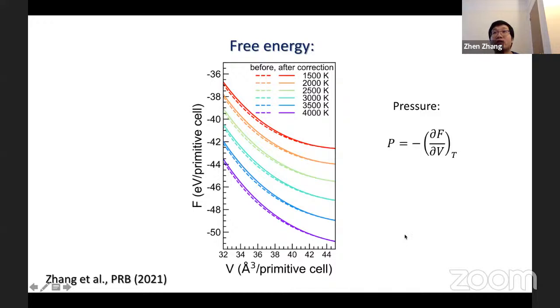Next, the free energy was obtained by entropy integration. Results obtained before and after the EOS correction are shown as dashed and solid curves, respectively. Note the DFT energy correction is temperature independent and does not include anharmonic effects. Anharmonicity, in principle, is adequately addressed by the temperature-dependent phonon quasiparticles and included in the vibrational part of the free